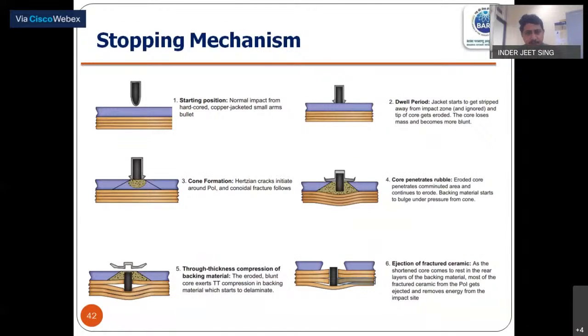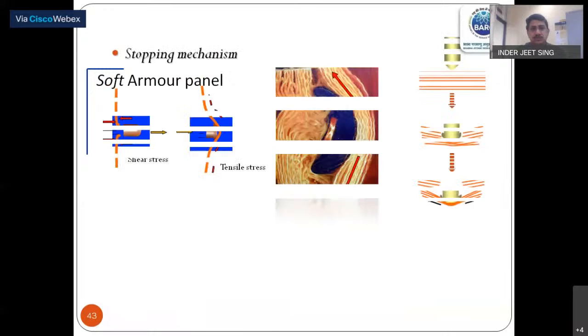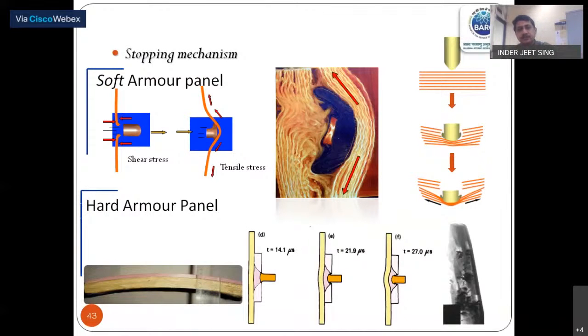If we see the stopping mechanism, if the bullet comes, it first hits the hard ceramic, it gets blunted and the jacket of the bullet gets ejected, and the core comes and makes a fracture on the ceramic, and slowly it passes through the ceramic and then comes in contact with the backing material, which is a layered structure. Initially a few layers get torn and finally it gets trapped. So those are the steps. This is the same thing with some pictorial views.